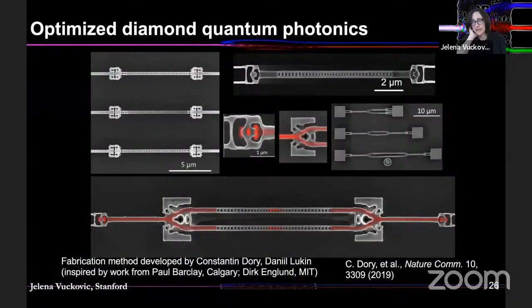So for diamond, you can't get really thin film diamond on an insulator commercially. You have to make it yourself, or you have to do some kind of bulk carving to make photonics, and that's what we do. It's a method that was pioneered by Paul Barclay at the University of Calgary, and then it was adopted by us and others. And it's really essentially carving. You start from a bulk block of diamond, and then you lithographically define whatever you would like to fabricate, and then you etch down, and then you etch sideways, and then you end up with these suspended structures that I think really look beautiful, thinking that this is a block of diamond.